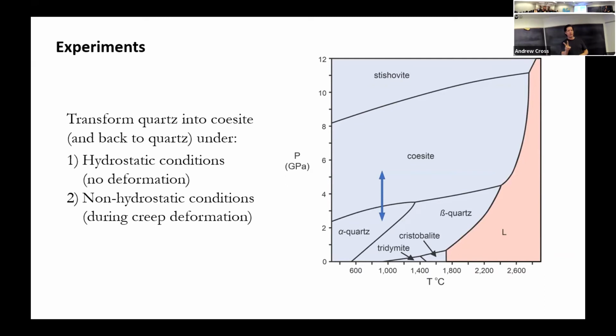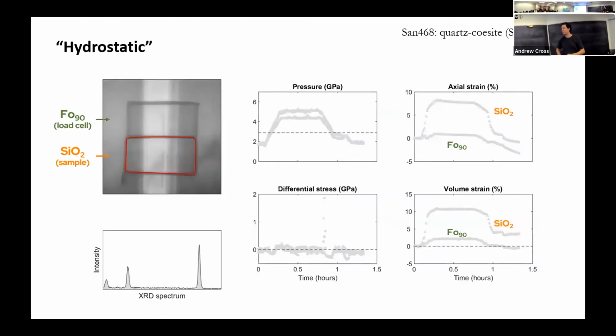We've got two main types of experiments. We've got these so-called hydrostatic experiments where we're not going to apply any differential stress to the sample. We're just going to increase pressure and then bring it back down. And then we've got our second set of experiments, which are these so-called non-hydrostatic ones, where we're actually applying a differential stress. So we're deforming the sample as it's going through the phase boundary.